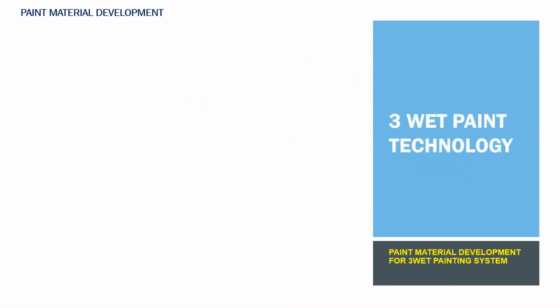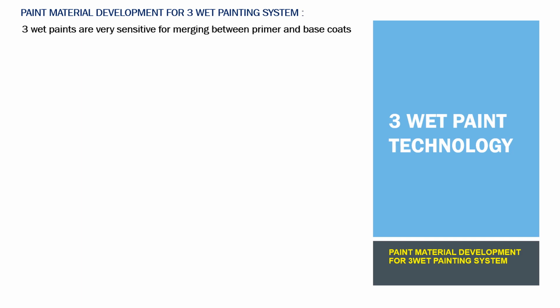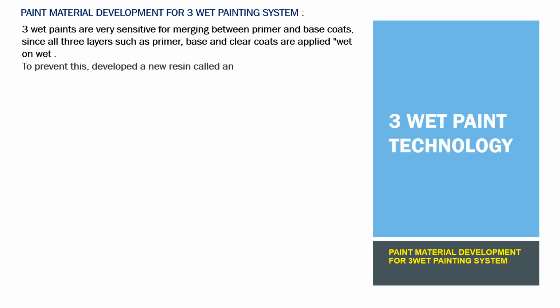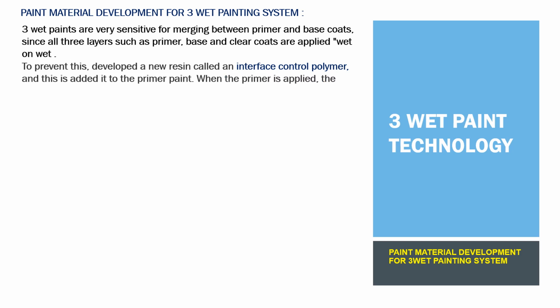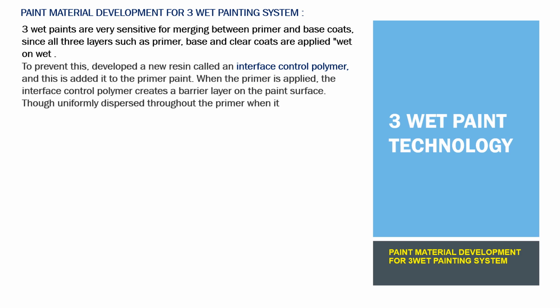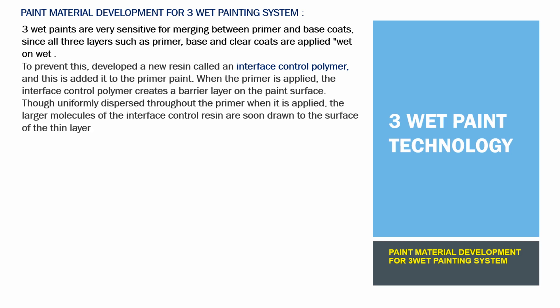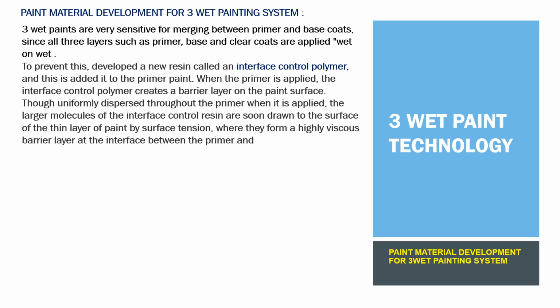Paint material development for 3-wet painting system. 3-wet paints are very sensitive to merging between primer and base coats, since all 3 layers, primer, base and clear coats, are applied wet on wet. To prevent this, a new resin called an interface control polymer was developed, and it is added to the primer paint. When the primer is applied, the interface control polymer creates a barrier layer on the paint surface. Though uniformly dispersed throughout the primer when it is applied, the larger molecules of the interface control resin are soon drawn to the surface of the thin layer of paint by surface tension, where they form a highly viscous barrier layer at the interface between the primer and base coat.